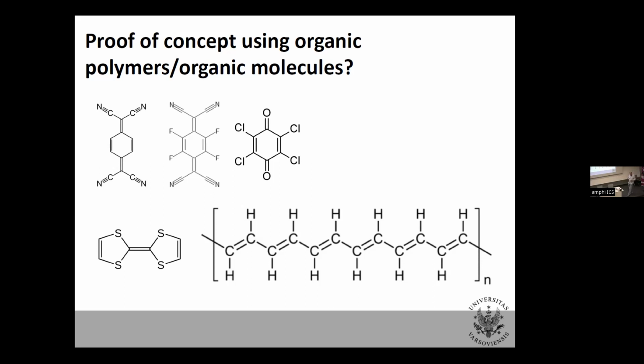And now the idea is, could one construct a prototype of this chemical capacitor using some organic molecules or organic polymers? Let me emphasize again that the idea is not to take undoped organic polymer. In fact, my master's has been done on organic polymers, so I have some affinity to conducting polymers. But the idea is not that you take an undoped system and you dope it chemically or electrochemically. This is trivial. Everyone knows this since the 80s. But the idea is that you take two non-conducting parent compounds, stoichiometric ones, and you put them separated by some inert separator, for example, polyethylene, and they metallize each other by proximity.